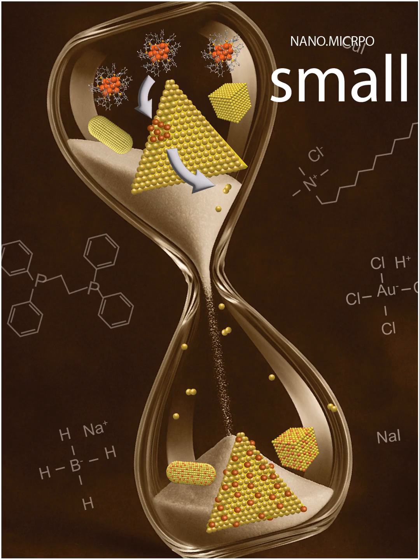Right, so the thinking is the initial Cu18 cluster probably breaks down slightly in the solution, forming some reactive copper complexes, maybe like Cux-DPPE. These complexes then interact with the gold nanotriangle surface. And the DPPE molecules, the phosphine ligands, they're attached to the copper, right? Yes, they act like little chemical handles. And they seem crucial. The researchers suggest that maybe some gold atoms on the surface aren't perfectly covered by the original stabilizing surfactant molecules used to make the triangles. Little gaps in the protective layer? Potentially. These slightly exposed gold atoms might be the starting points. The DPPE ligands on the copper complex might then bridge the copper to these gold atoms, sort of lowering the energy needed for an exchange to happen. Like a molecular facilitator? Kind of, yeah. Facilitating the swap.